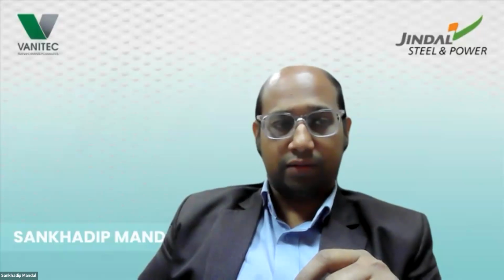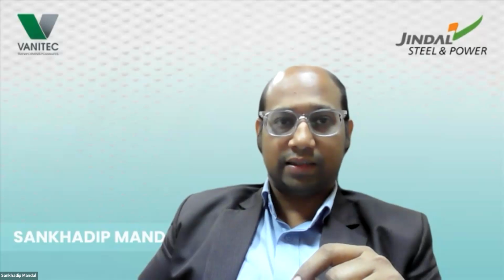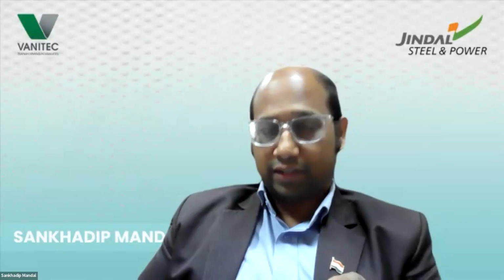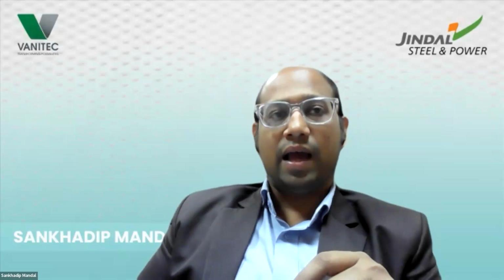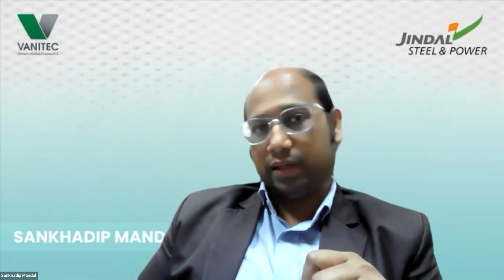But in the case of vanadium additions, or vanadium carbonitride, because it starts precipitating at lower temperatures, in most cases the stressed regions of the continuous caster are already overcome, and then it will start precipitating. So vanadium has an added advantage if I compare it with the other alloying elements. It improves the hot ductility behavior of the material, and it also avoids a lot of quality issues in the high tensile, high strain grades.